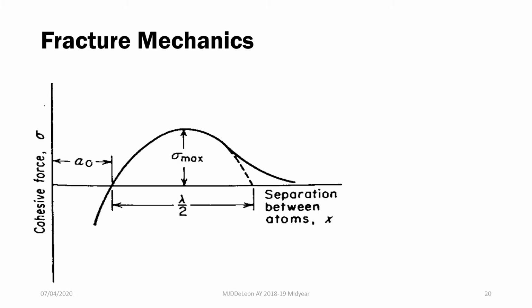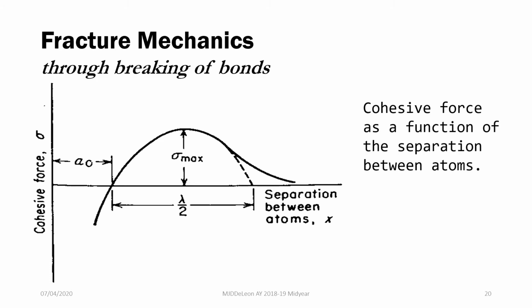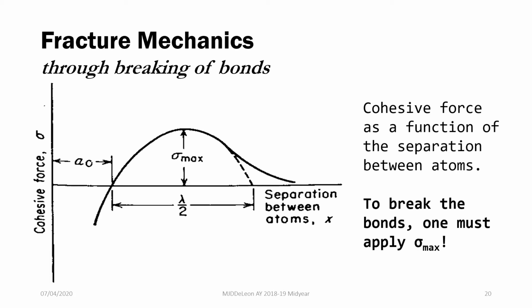Looking at the atomic scale, the mechanism of fracture happens through the breaking of our bonds. So, meron tayong tinatawag na cohesive force. Your cohesive force is a function of the separation or the bond length, bond distance between your atoms. Essentially, to break the bonds between two atoms, we must apply a force greater than the cohesive force of your atoms. Or we must apply a force greater than this sigma max here. Pag mas mataas yung force na apply natin than the bond force or the bonding force between your atoms, we have a very good chance of breaking that bond, leading to the fracture of your material, possible fracture.